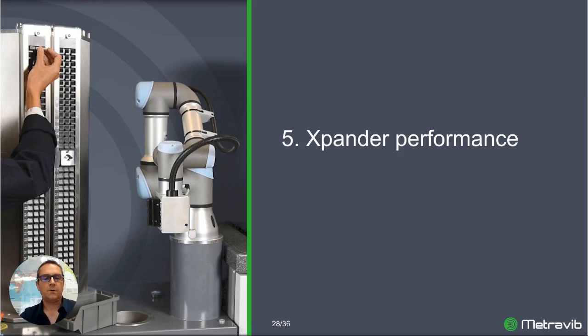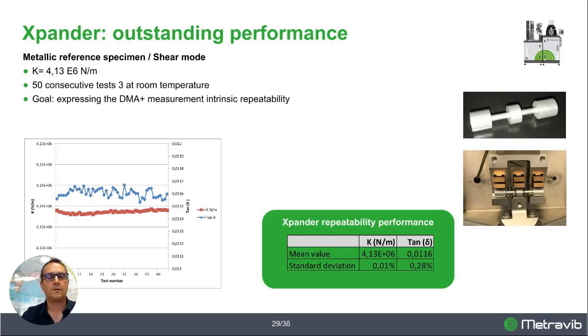So let's have a look at Xpander performance. The first test corresponds to 50 consecutive tests at room temperature. The goal is to express the DMA measurement's intrinsic repeatability, and you can see that the standard deviation we get on the stiffness we measure is roughly 0.01%, and on tangent delta 0.28%. In this case, the specimen is a metallic specimen with a middle-range stiffness, and that already gives a very good idea of the performance of the system.